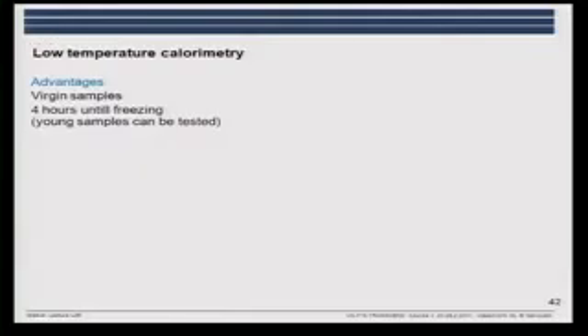The advantages of this method are that we can use virgin, non-dried samples. It doesn't take that long to freeze, so the samples can be fairly young. It takes 4 hours or so until they freeze. But of course, it depends on your cooling rate. We are at DTU using samples the size of my thumb, very large. Others are using much smaller samples, and they can have a more rapid cooling.